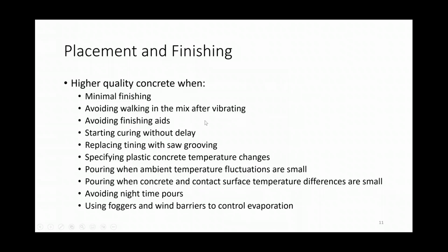And then there was a discussion about specifying temperature changes for plastic concrete, or trying to pour when the ambient temperature fluctuations were small, or at least when the concrete and the contact surface, so that would be the girder, are similar. If the concrete and the girder temperatures were very different at the time of the pour, it seemed like it was causing more trouble, and avoiding nighttime pours for that same reason. So controlling temperature as much as you can seems to result in better quality concrete.